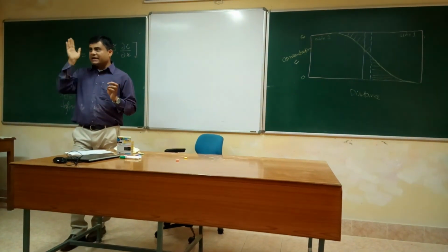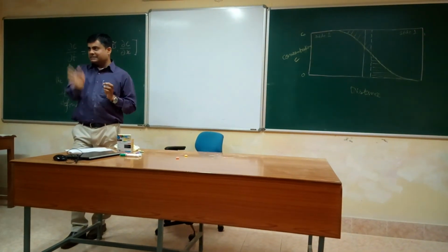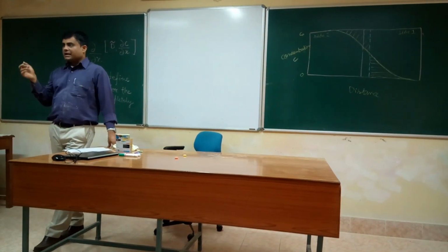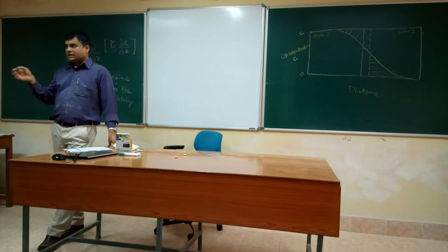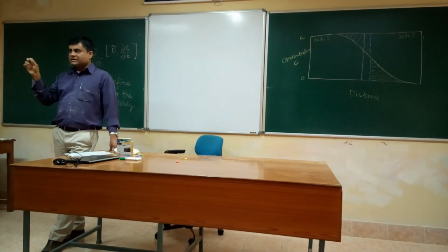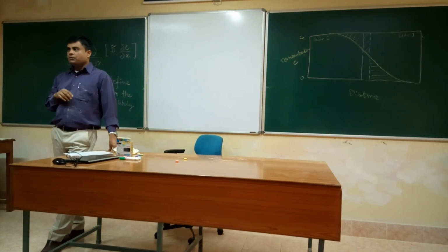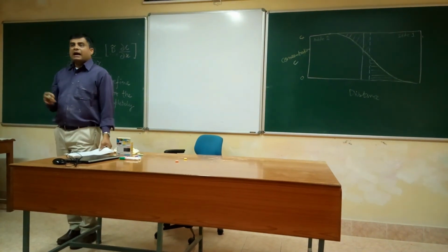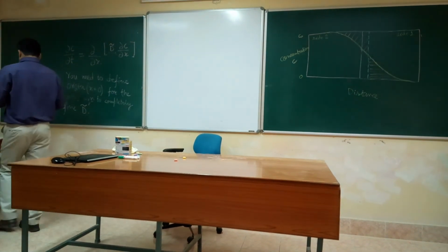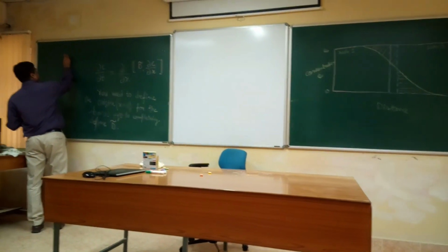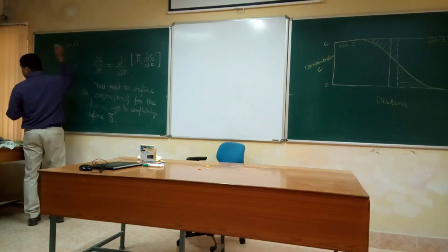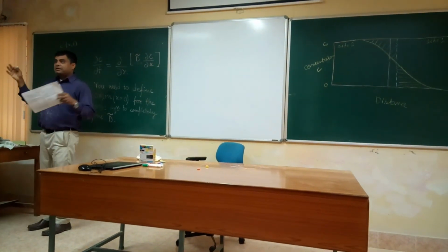Then you section through at different distances, and count the number of isotopes in each section at a particular distance x from that interface. So you get the concentration profile of the tracer, from which, for this boundary condition, the solution of the equation is C(x,t) for the case I just described.